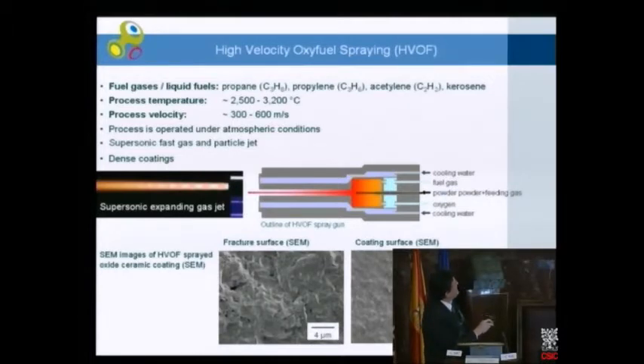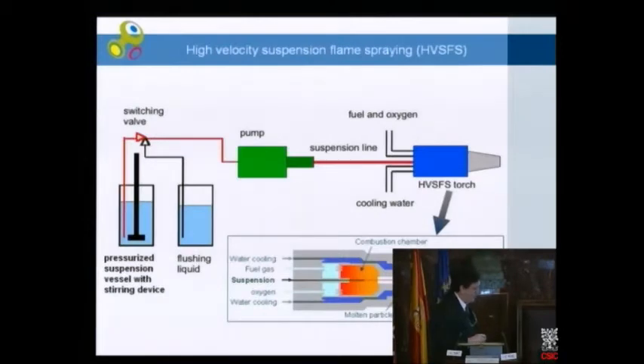But the nice advantage, and you can see it here in this picture, there are 1, 2, 4, up to 6, 7 nodes. Those are the Mach nodes, and you see the velocity of the gas jet can exceed 5 or even 6 times the speed of sound. And that makes it so challenging to inject our ceramic powder into this high-pressure combustion chamber, use the strong acceleration, and use the impact to make the final coating. But we have this intensive heat and mass transfer and also momentum transfer. And today I will not go into any detail on the experimental results so far, but will show you the outcome from the viewpoint of building a model and using simulation techniques to predict, and not only to predict, but also to optimize the processes.